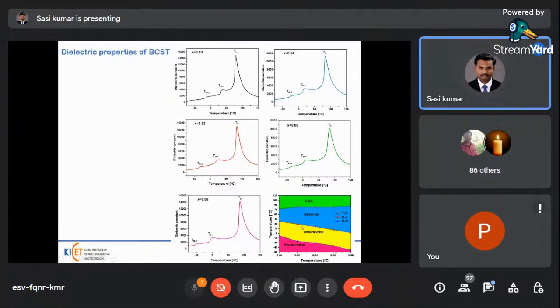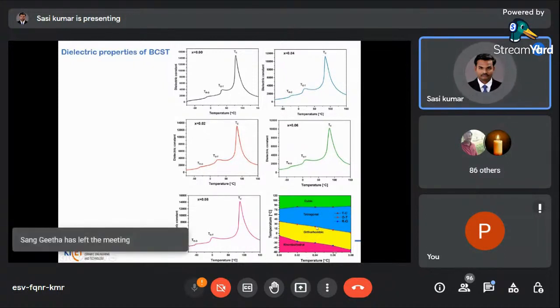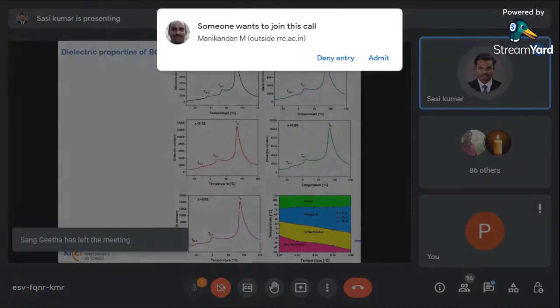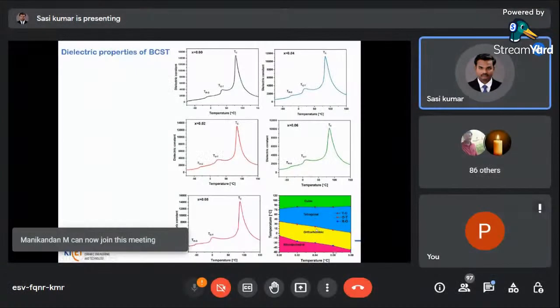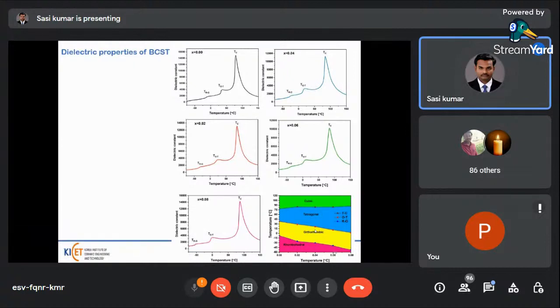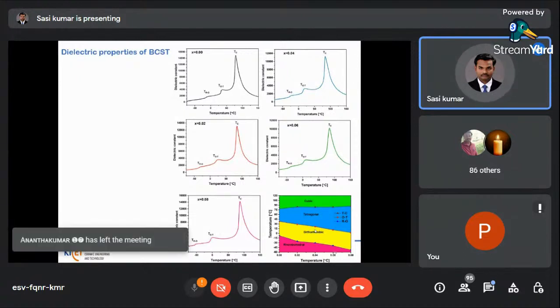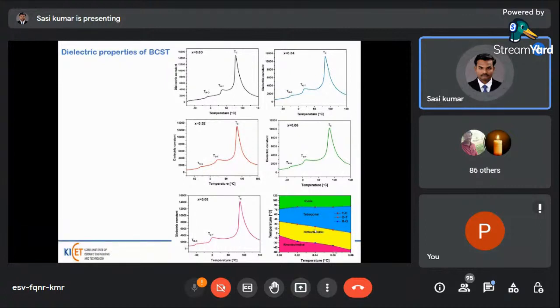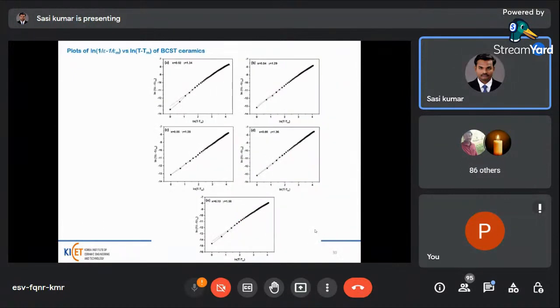So around 0.04 composition possesses two different structures, orthorhombic and tetragonal. So at room temperature, the x equal to 0.04 composition possesses orthorhombic and tetragonal structures. So it is mentioned as a morphotropic phase boundary of this composition. Okay.